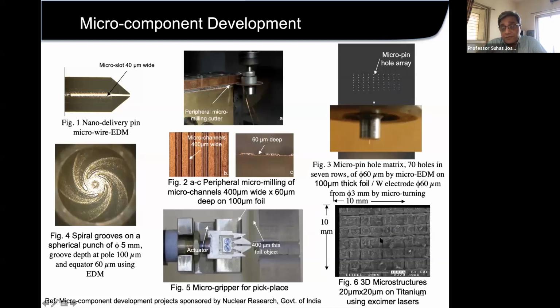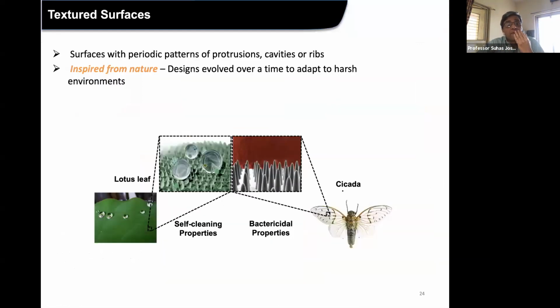And these are some of the initial textured surfaces by lasers, but we did a lot of things later on. So from here, we have been doing different work, but this is some textured surfaces manufacturing using EDM, using the micro machining processes. So these are some of the textures which are there on the wings of cicada. So these are like sharp peaks which are there on the surfaces of cicada. And when the bacteria fall on it, the bacteria actually pierce on them and they die. Whereas here, these are the globular kind of structures, multi-scale structures, like larger globules at the bottom and smaller on the top of it and smaller on the hairs on the top of it, like multi-scale structures, which are good for self-cleaning kind of properties.